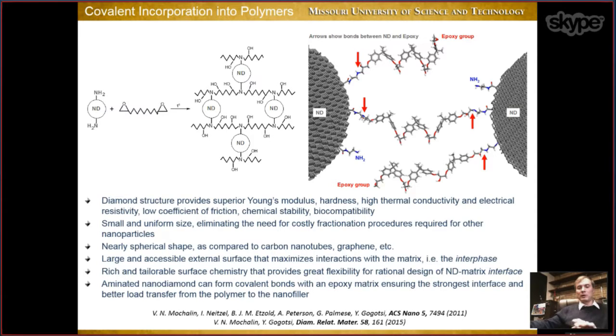You add nanoparticles, but it doesn't result in any improvement in mechanical properties, okay? Because the load cannot be transferred to those particles. So in this case, we solve this problem because we produce the strongest possible interface between polymer and nanodiamond. We produce covalent bonds, and there is nothing stronger than that. I mean, what is stronger than covalent bonds? Probably nuclear interactions, but we don't know how to manipulate them. So covalent bonds are the strongest interface we can make. And this is what we do by mixing aminated nanodiamond with epoxy. So this is a molecular model of what we expect to achieve. And now let us see what we got in the experiment.